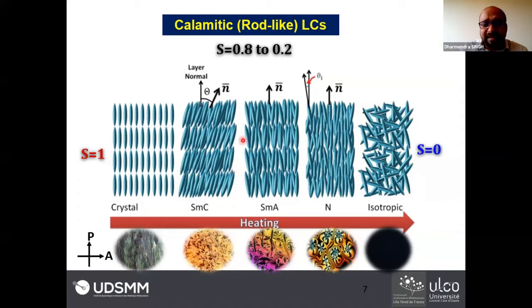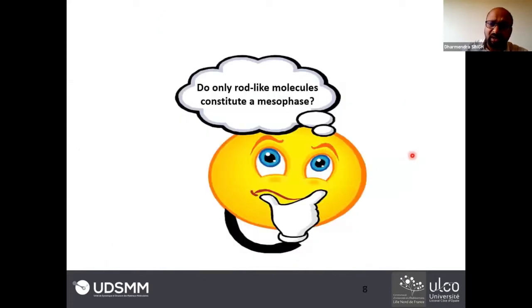The beauty of this phase is that you can believe it by seeing it, because we belong to the scientific community and we do not believe until we realize or see directly. When you see different phases of liquid crystal molecules under a polarized optical microscope, you get different optical texture images. By analyzing these textures, you can assign which mesophase or liquid crystalline phase it is. Until 1977, it was a myth that only rod-like molecules can constitute a liquid crystalline mesophase.